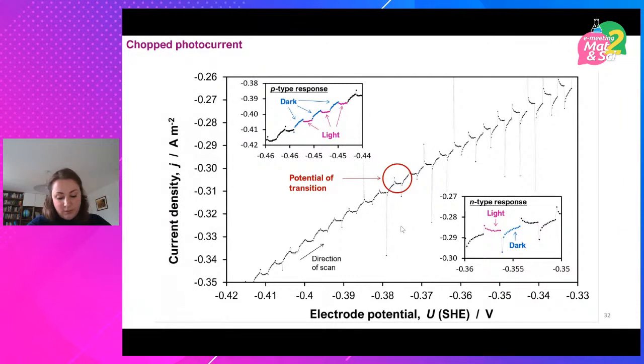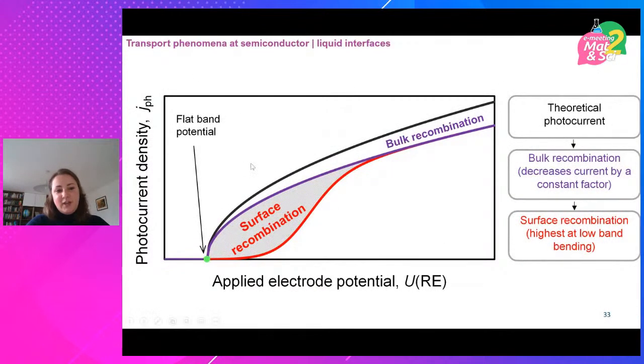So I know I'm already at 45 minutes, but I just wanted to very quickly introduce the work that my colleague Frankie continued. So this was the work with all the flat band potential. Having done all of that just to determine the flat band potential, you then have to model the rest of the kinetics that accurately account for all of the losses that happen. So the bulk recombination efficiency, the surface recombination efficiency, that's a function of applied potential. And then in some cases, there's also the Faradaic efficiency. So what fraction of the total current actually is the process that you want? And it's not always 100%.